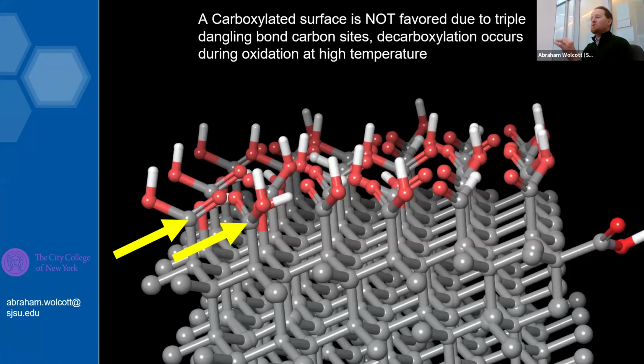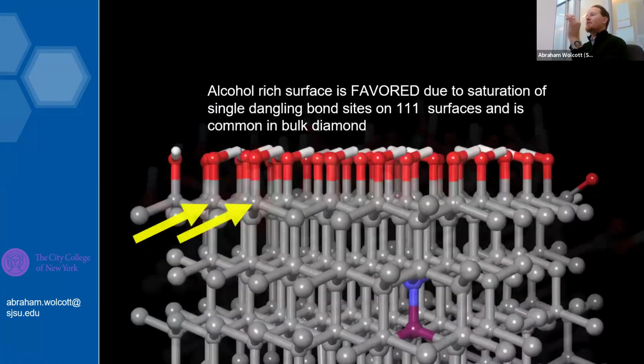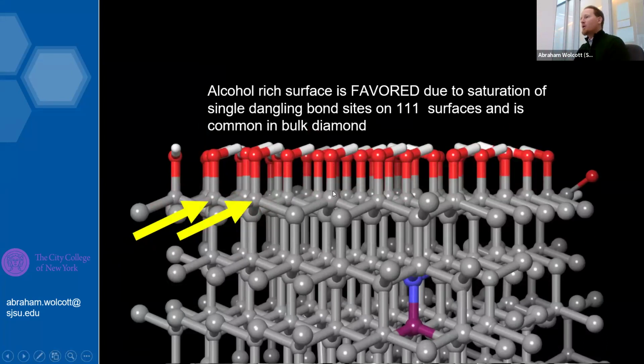Instead, the way we should be viewing it is that we've got this type of surface where we mostly have alcohols and the occasional carboxylic acid on steps and facets and on edges of our crystallite. And we would say the alcohol-rich surface is favored due to saturation of single dangling bonds on the 111 surfaces. And this is common in bulk diamond. I can share with you many pieces of literature that show that alcohols are readily found on bulk diamond surfaces. And of course, we've got the NV that's hanging out right there.